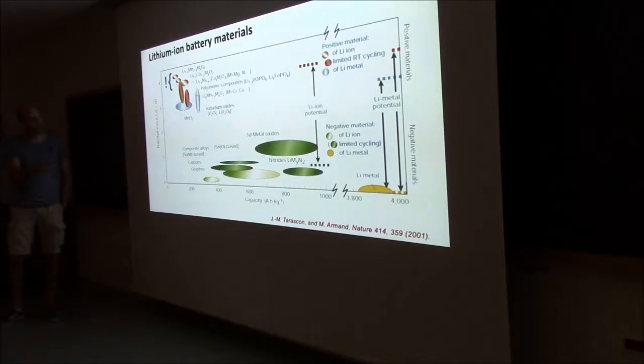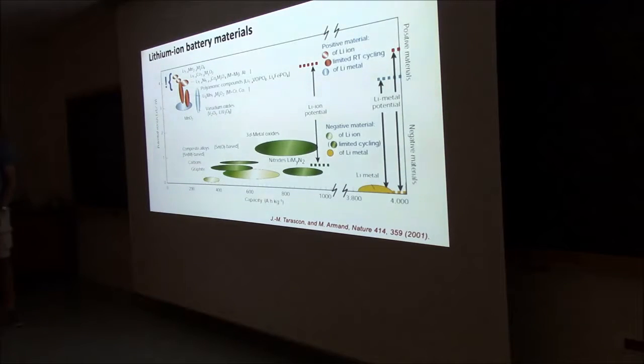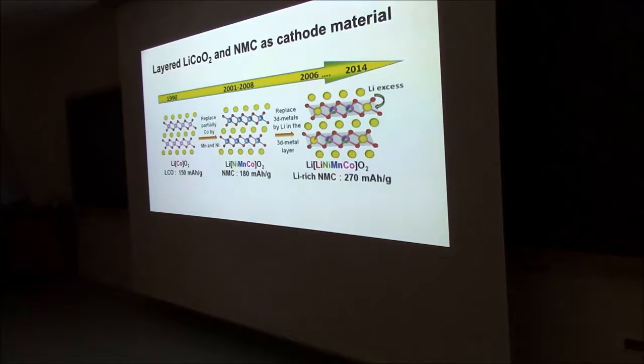So a couple of years ago we decided to start looking into these oxide materials. These are materials with crystal structures, which is very common to us. We said, okay, let's grow them by pulsed laser deposition in our lab, and let's see what we can achieve. From these materials, I told you lithium cobalt oxide was the starting point in the 90s for Sony. It wouldn't stay the same over the years. So you can see here lithium cobalt oxide with the energy density. Here you can see the cobalt oxide planes with the lithium in between.